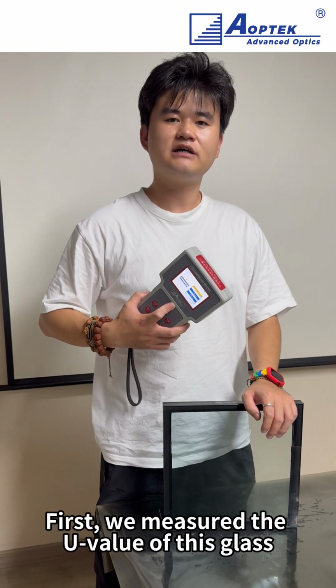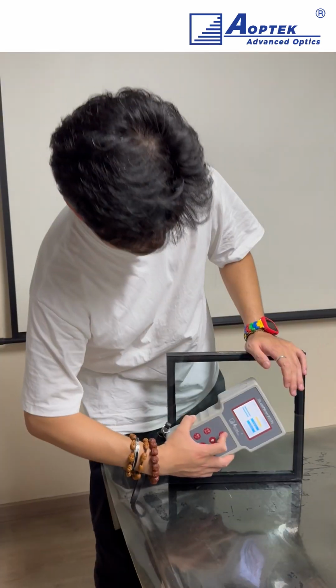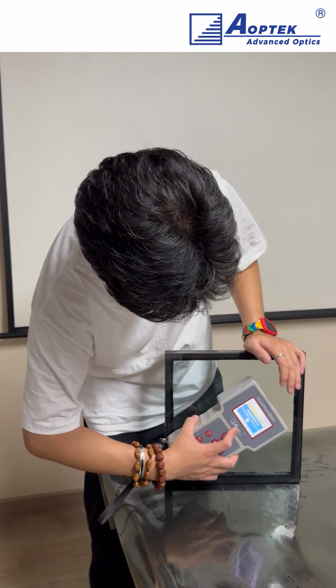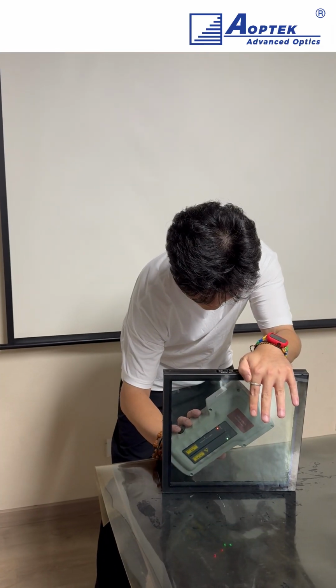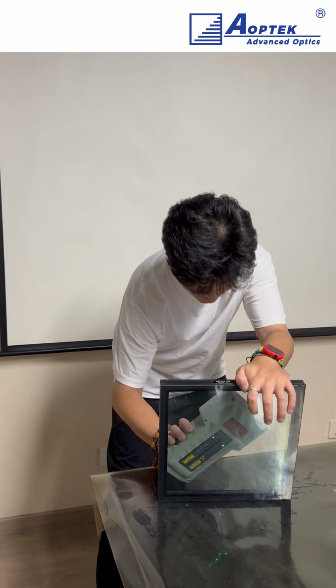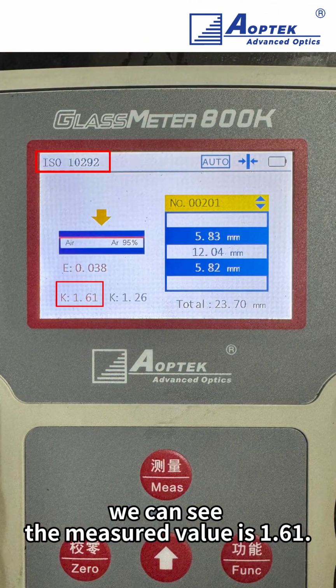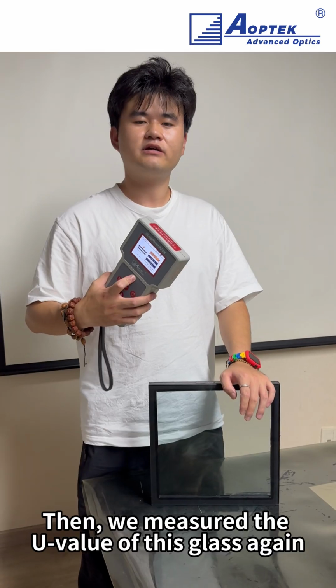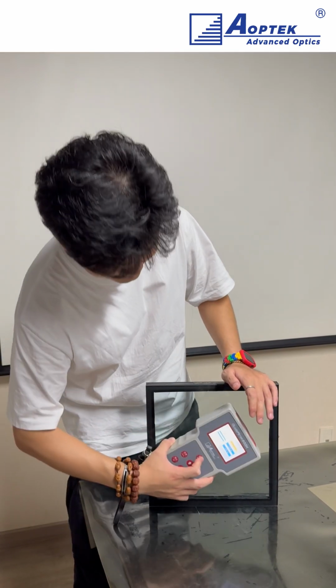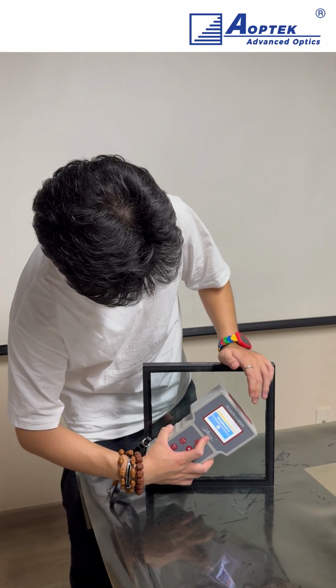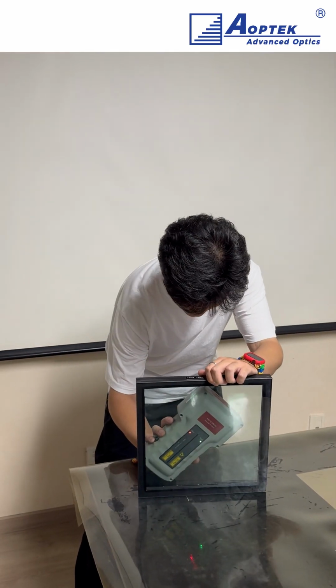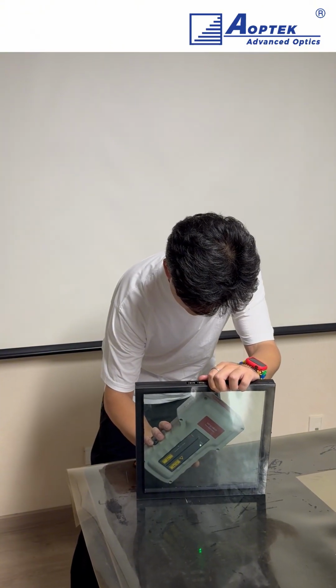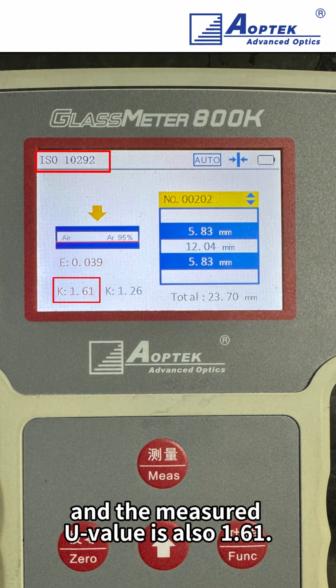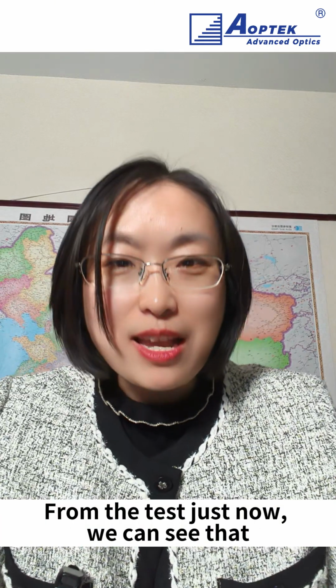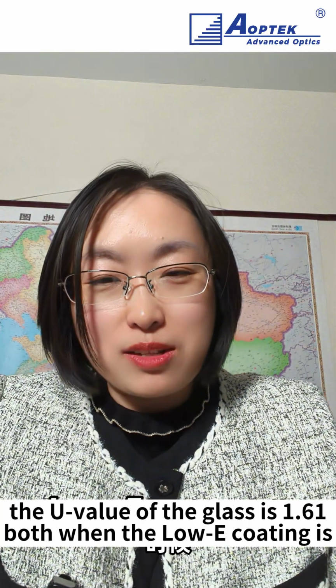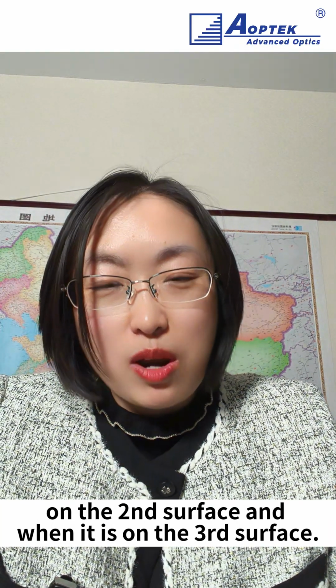First, we measured the U value of this glass when the Low-E coating is on the second surface. We can see the measured value is 1.61. Then, we measured the U value of this glass again when the Low-E coating is on the third surface. And the measured U value is also 1.61. From the test just now, we can see that the U value of the glass is 1.61 both when the Low-E coating is on the second surface and when it is on the third surface.